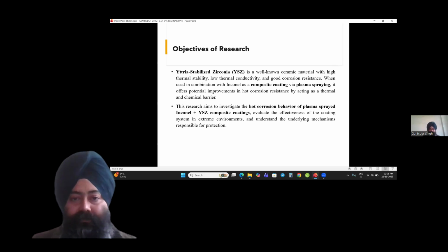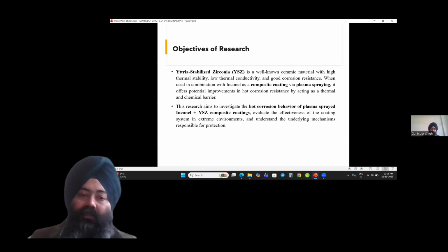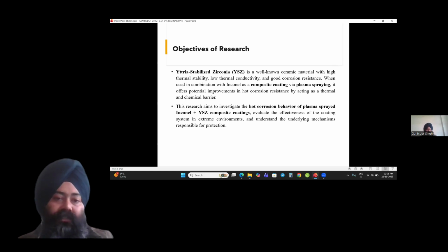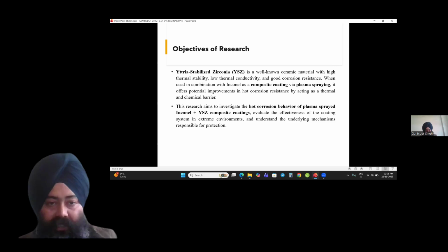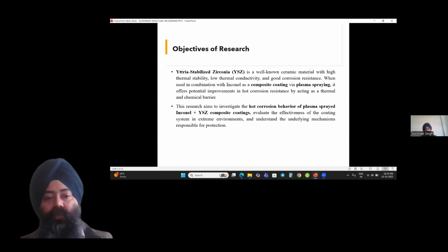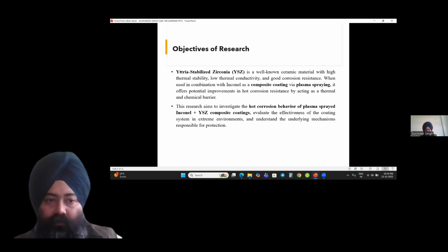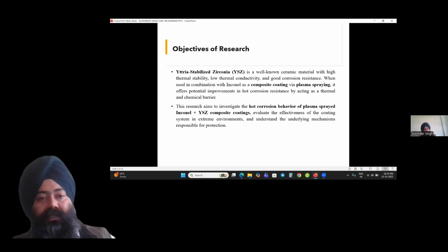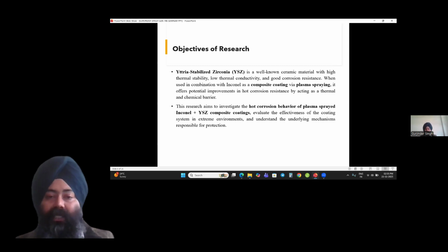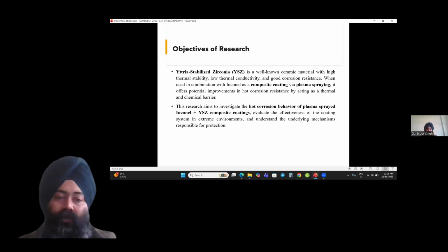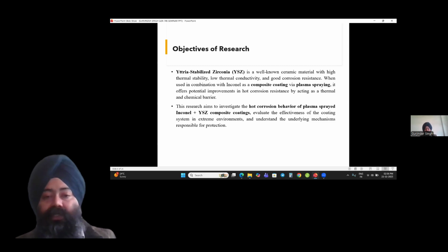Now, what are the objectives of the research? In our research, I am planning to study a well-known ceramic material, that is yttria stabilized zirconia, which has high thermal stability, low thermal conductivity, and good corrosion resistance. But I am not planning to simply coat YSZ on the material. We use YSZ in combination with Inconel as a composite coating. And we are planning to do that coating via the plasma spraying technique. Why plasma spraying? Because it offers potential improvement in hot corrosion resistance by acting as a thermal chemical barrier.